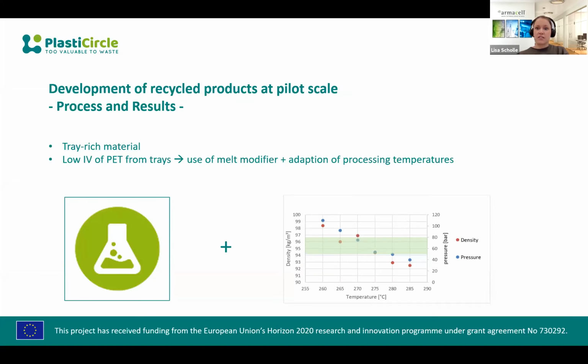So let's move on to the results from the development of recycled products on pilot scale. The raw material for the foam board production on pilot scale was selected based on the screening and the recipe development on lab scale. So we used a tray-rich material with up to 20% of tray. As we learned before, PET from trays has a lower viscosity, and therefore the use of melt modifier and the adaptation of processing temperatures are needed to keep the pressure on one side and also to achieve optimal foaming conditions.